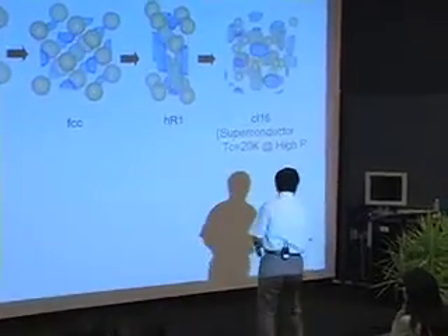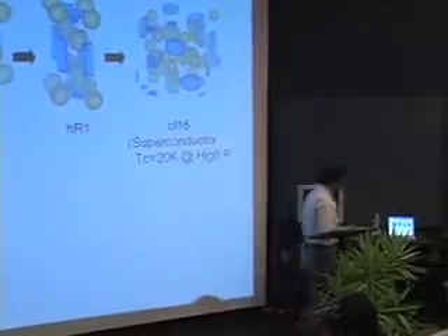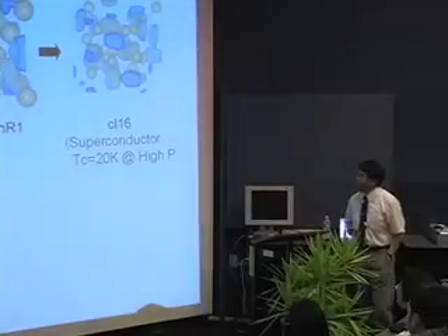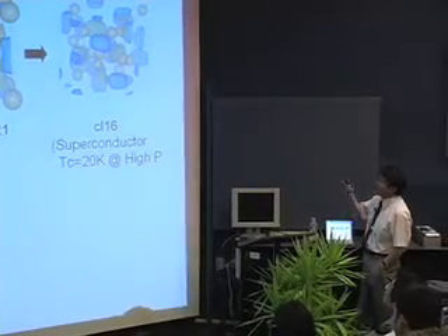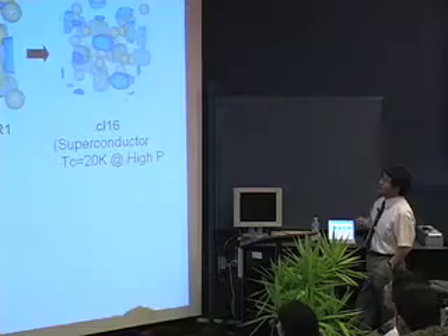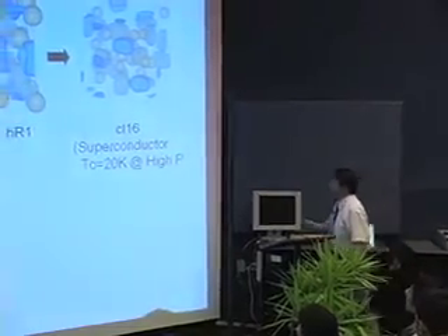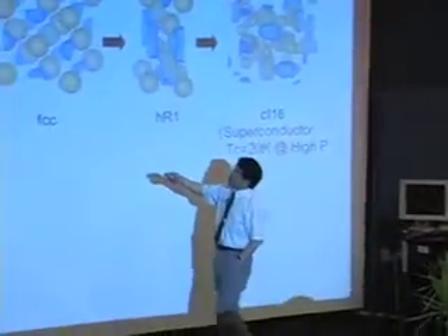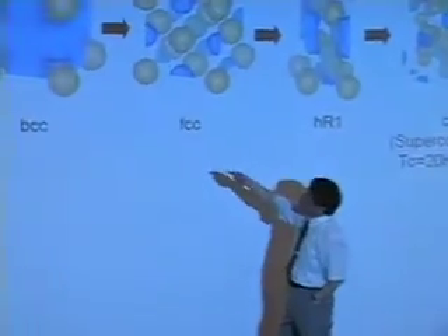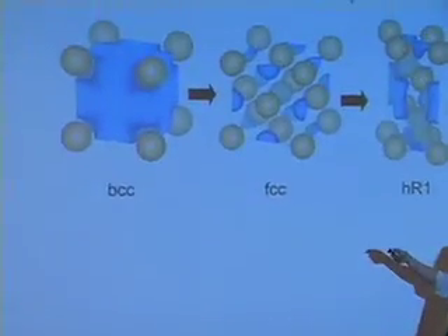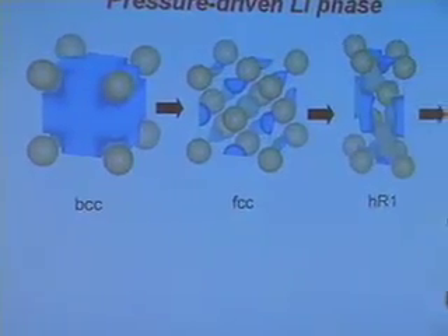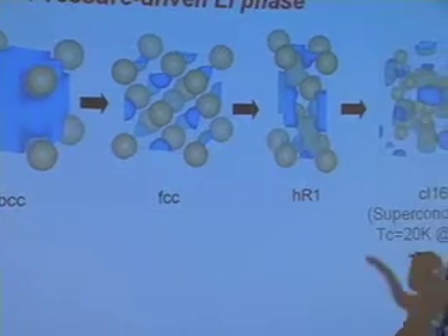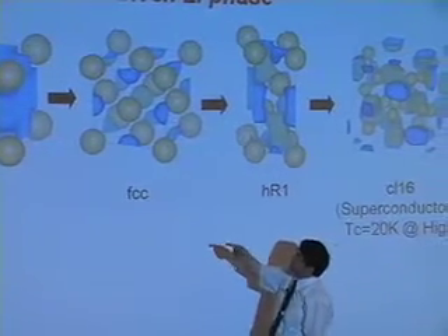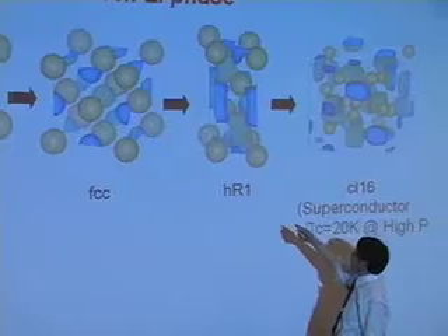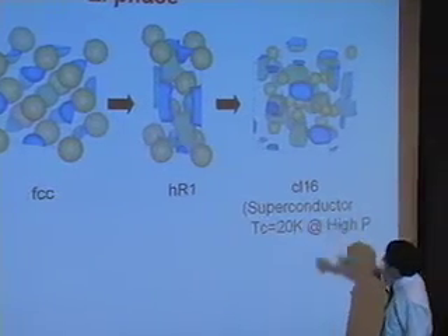So we checked the correlation between our C12A7 and the high pressure superconducting phase of lithium. This is the case of lithium. At ambient pressure, BCC is the crystal structure of metal lithium. When pressure is applied, it changes to FCC, then HR1, and eventually cI16 phase.